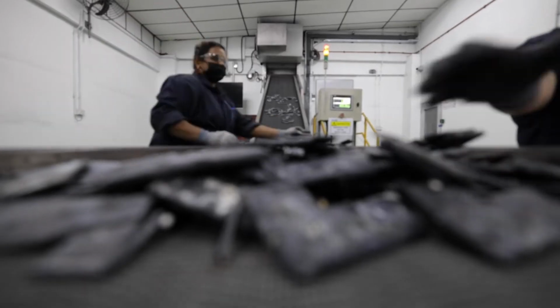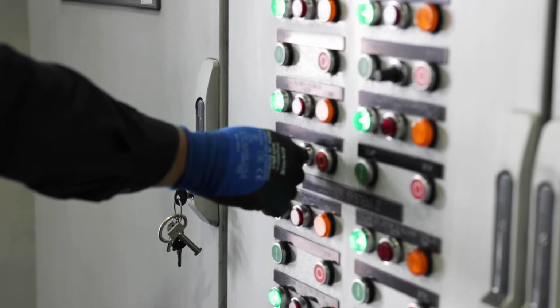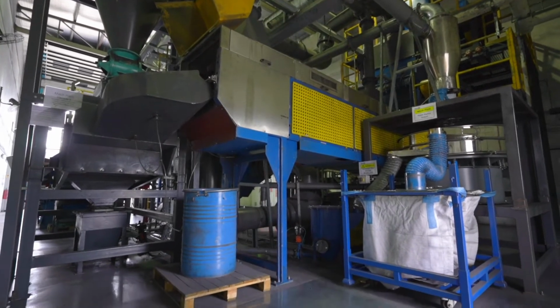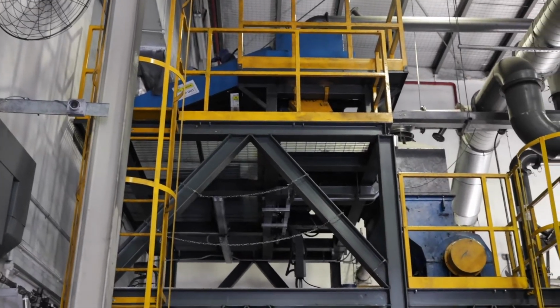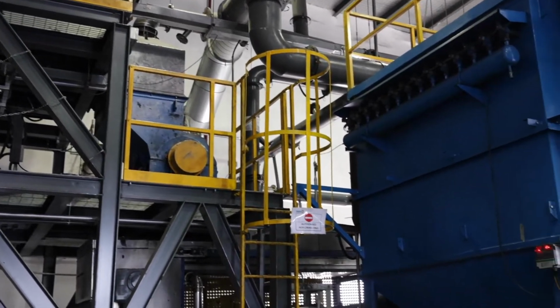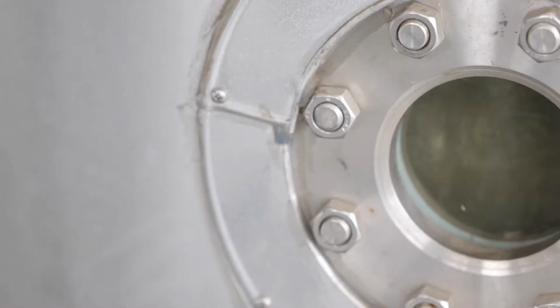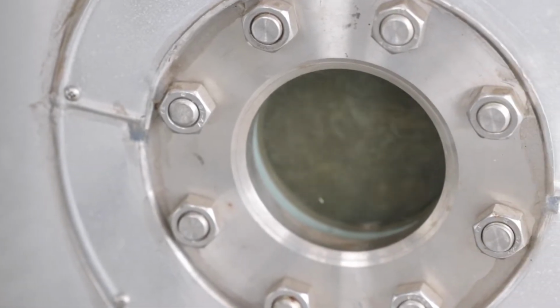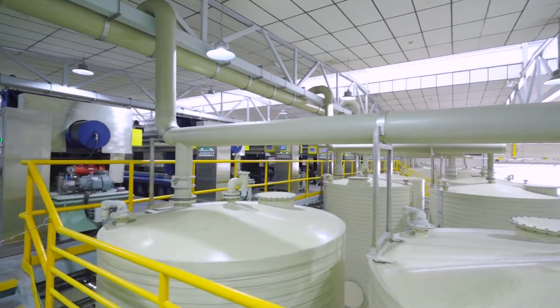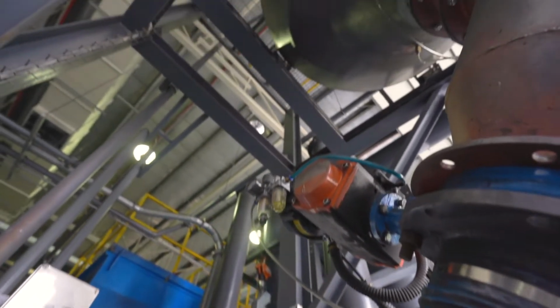Once segregated into battery types, the components go through the mechanical process, which is broken into two phases: size reduction and separation. First, the batteries go through a series of intense shredding and hammer milling, while thermal runaway is minimized. The process heat still allows the electrolytes to evaporate and be captured as VOC gases, all closely monitored to maintain safety levels.